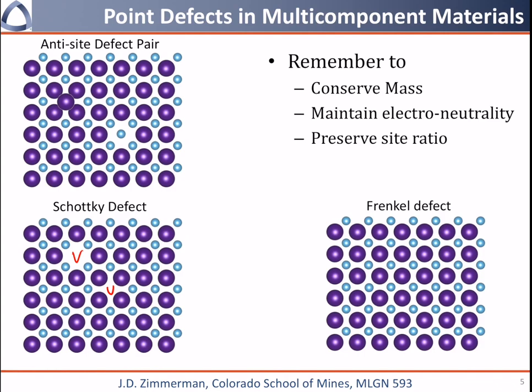The last type of defect I want to talk about is a Frenkel defect. A Frenkel defect is the combination of a vacancy and an interstitial. We've taken this atom and moved it from its site over to an interstitial position. In a lot of materials these are hard to form, but they show up in some interesting situations — one of them is radiation damage. If you send really high energy particles into a crystal, it may literally knock an atom out of place and it will stop somewhere after giving off enough kinetic energy.